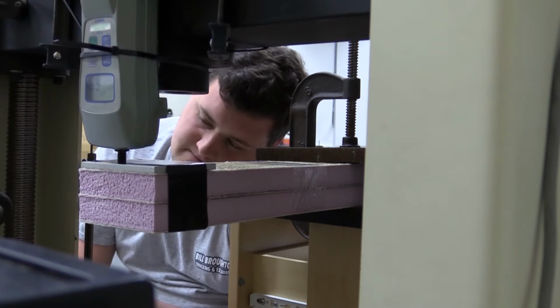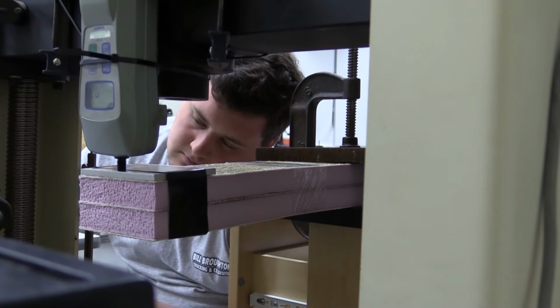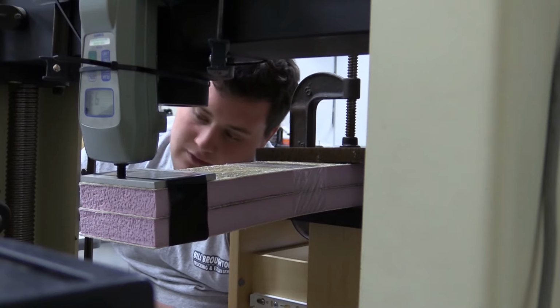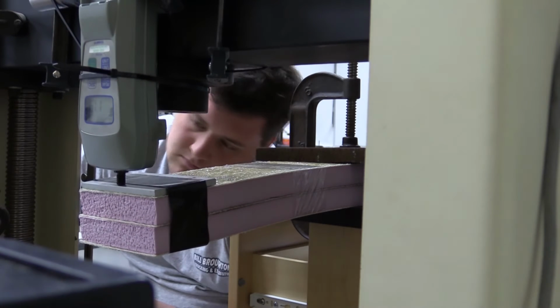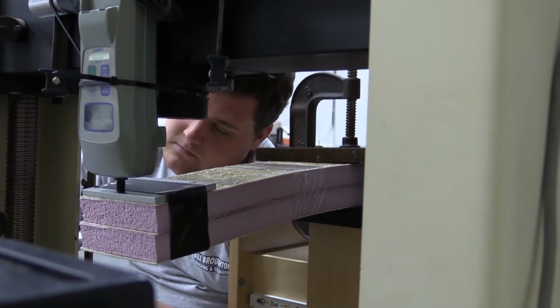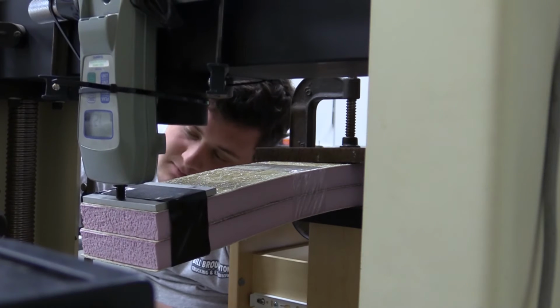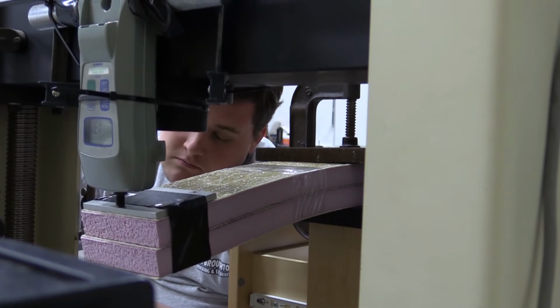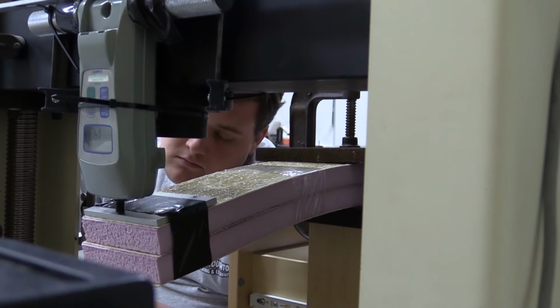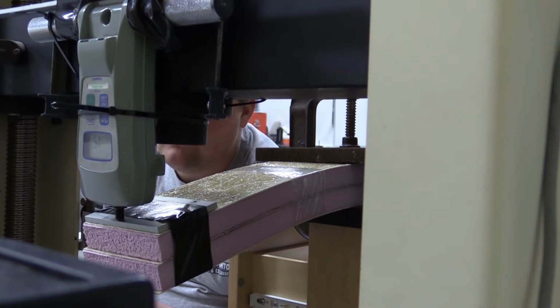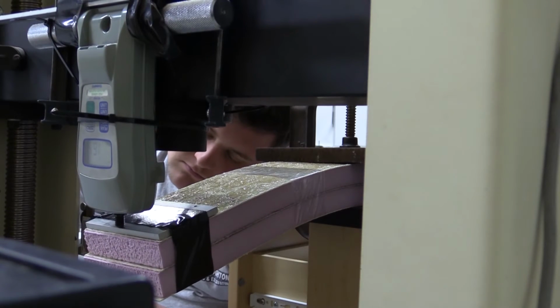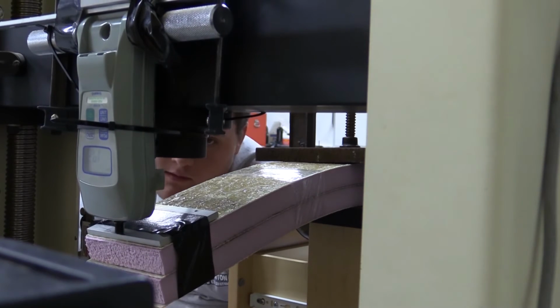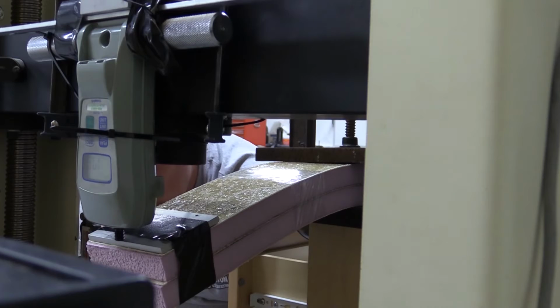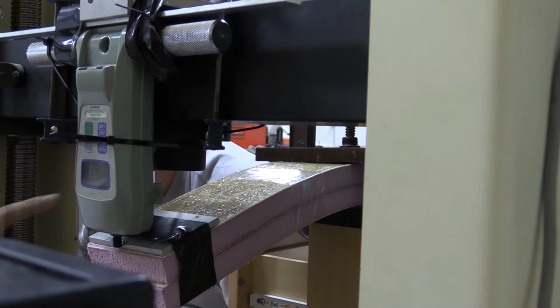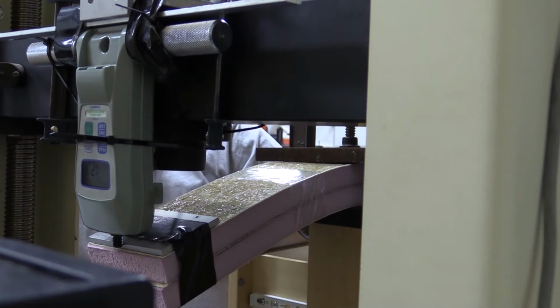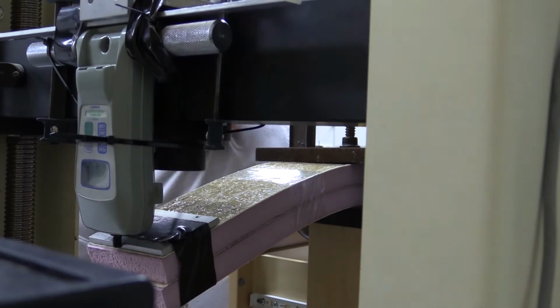Using the same methods of measurement as the sandwich beam, we tested the 3-layer composite beam. When doing this test, we found that the capacity of our machine to deflect the beam reached its limit, although we realized that that is all extraneous data, because with the fiberglass in the center of the beam, from our data you can tell that it almost immediately separated from the foam. And we think this is because with the fiberglass in the center of the beam, it was seeing the most shear, as the maximum shear in a beam is at the neutral axis.